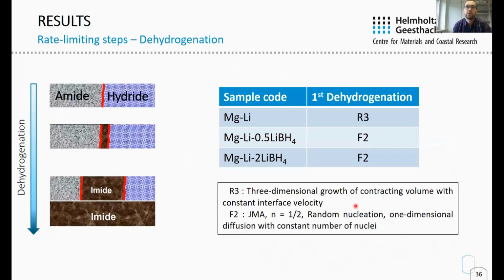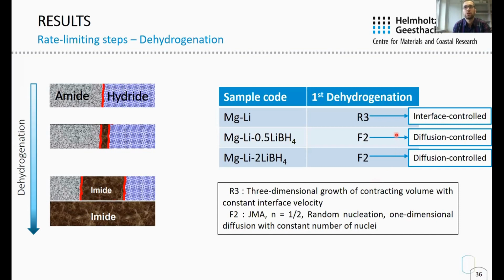In order to gain understanding about the intrinsic kinetic constraints, solid state models were applied to the first dehydrogenation and hydrogenation kinetics reactions using the Sharp and Jones method. In the case of the dehydrogenation kinetic behavior, it's possible to see that the rate limiting steps are different when the sample contains lithium borohydride. A pristine sample is controlled by an interface mechanism, while all the lithium borohydride containing samples present a diffusion control mechanism. It's clear that the reaction pathway for the lithium borohydride containing samples is different from the pristine one.